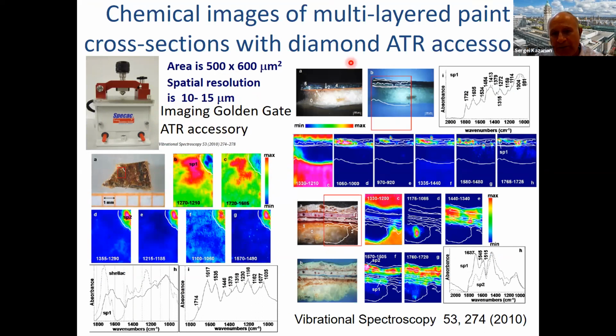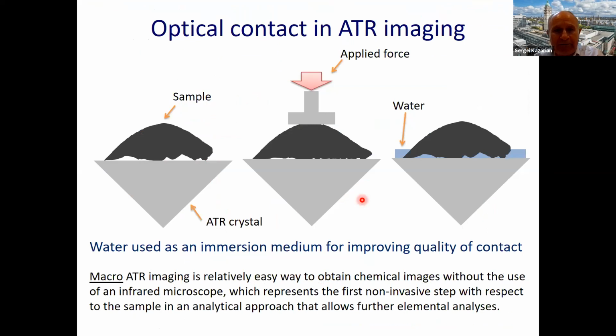And you can see that in most of them, we were able to identify and resolve the chemical composition of each layer. But the challenge was the following: with these samples we can press only slightly, not much, because you can break some very easily. And when the surface is rough, it shows a limitation of the ATR approach. However, here we added a droplet of water, which was possible with these samples, and we basically created an immersion liquid. We were able to obtain good spectra and images, and water was not interfering using this approach.